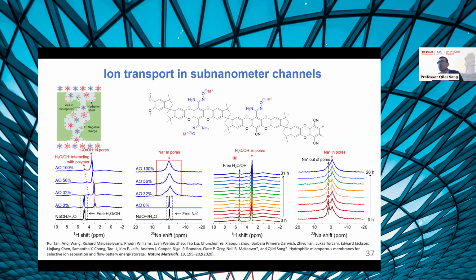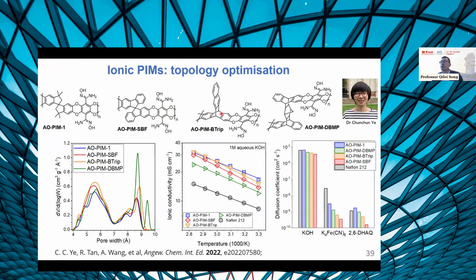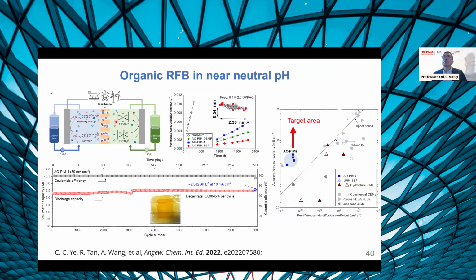You can see that this is the battery performance. And after this work, we also collaborated with Professor Neil McKeown because they have developed a wide range of PIM polymers for gas separation. So we were able to convert the nitrile group to amidoxime group, and then we can use all of these materials for ion conduction. You can see that some of these polymers give relatively higher conductivity in sodium and potassium hydroxide. And then we can integrate these membranes in the neutral pH organic flow battery. We got really good performance.